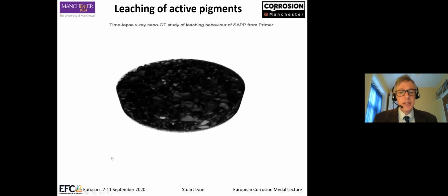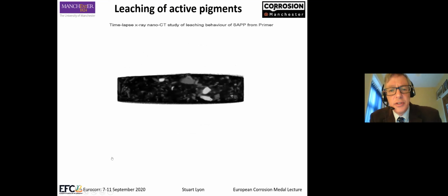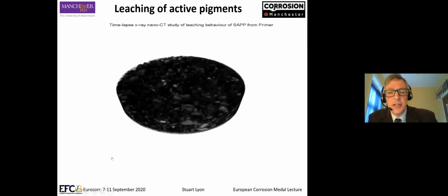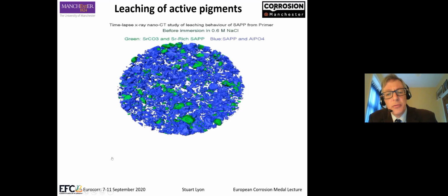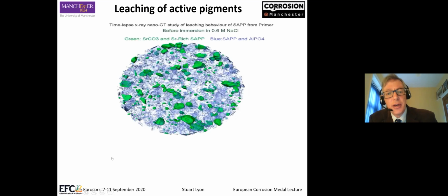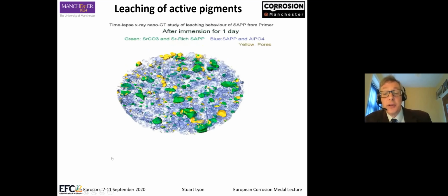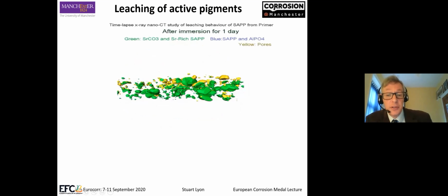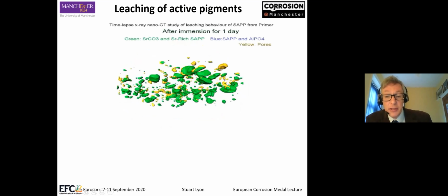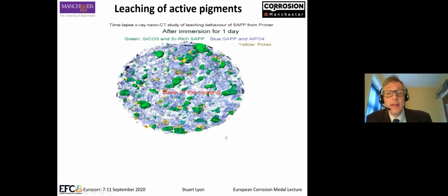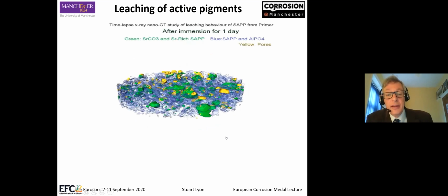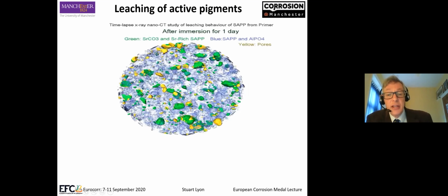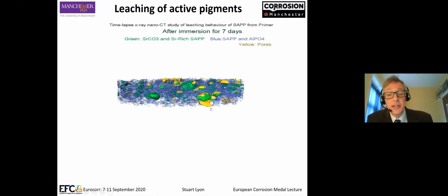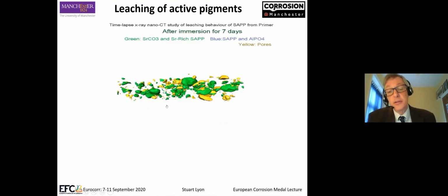Should run now, there it goes. This is a nano X-ray CT of leaching behavior from a particular kind of primer. We're color coding the contents of the primer now. The blue is the leachable component, and the yellow are the pores which are formed after a day of exposure. You can see the diffusion front just about penetrated through there. That's the back of the coating, and that's the front of the coating. And we can see these beginning to form connected pathways throughout the coating, sparse connected pathways, but connected nonetheless. And now they've penetrated after 7 days right the way through to the substrate, which is here.